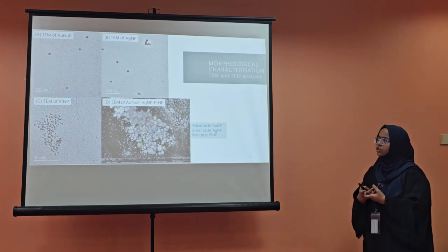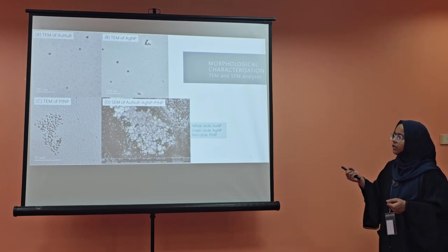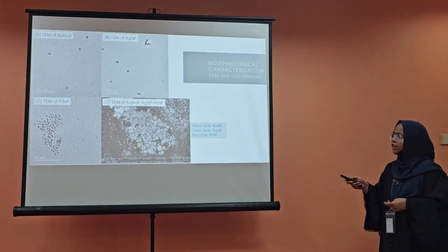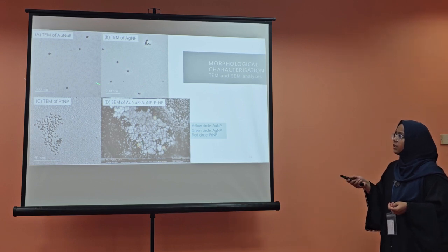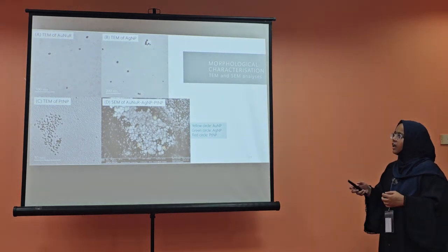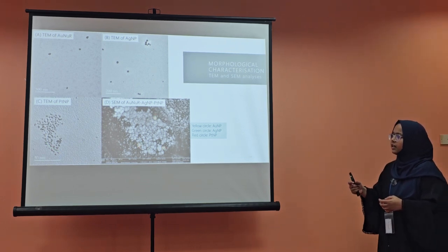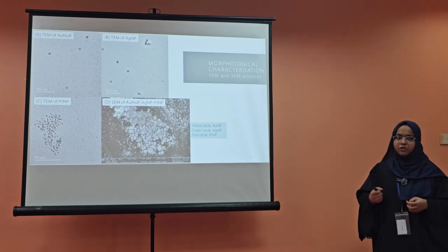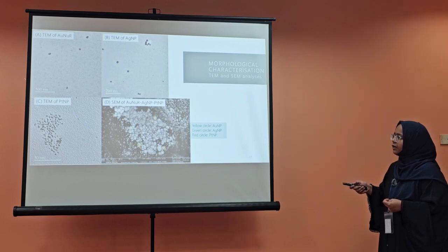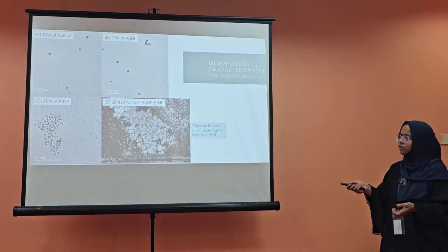The morphological characterization of the nanoparticles was done. TEM analysis of the individual nanoparticles was performed. Gold nanourchins, as you can see, have an irregular structure, and the average diameter is approximately 50 nanometer. Similarly, TEM images reveal that the silver nanoparticles had a spherical structure and an average size of 30 nanometer. Platinum nanoparticles were very small and had well-rounded structures with an average diameter of 5 nanometer. And some images revealed the formation of the nanocomposite, wherein the 3 different nanoparticles were present in close proximity, confirming the formation of the trimetallic nanocomposite.